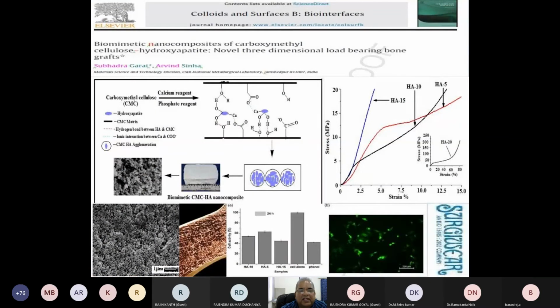Then my colleague, Dr. Subhadra Garai, took the process. She changed the polymer from gelatin or PVA to CMC, carboxymethyl cellulose. And the process was the same. Then she showed that such a nanocomposite has better mechanical properties, something like 20 MPa, and some superplasticity, that is very much likely because of the polymer, and this has bioactivity. This know-how was so liked by the industry that they immediately took it over. So Surgiwear has taken this know-how from us and they started developing it into a commercial product.